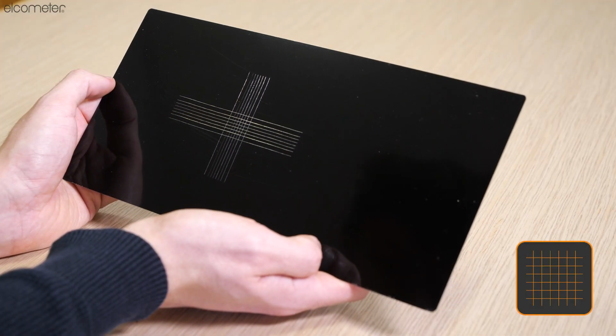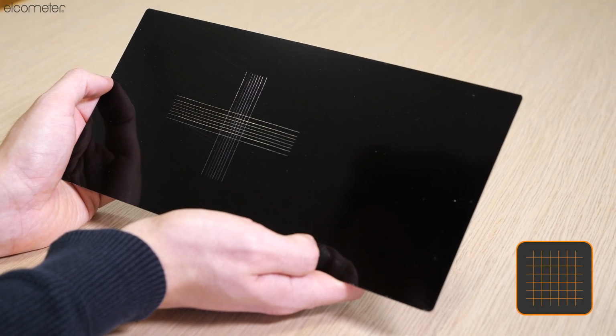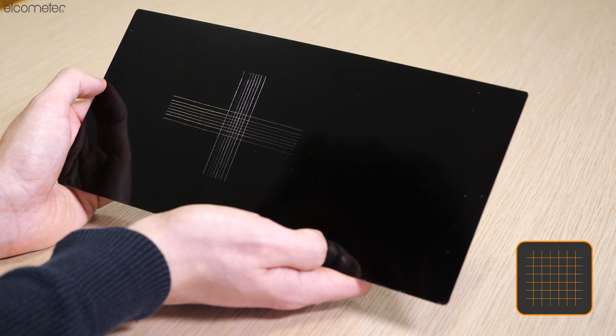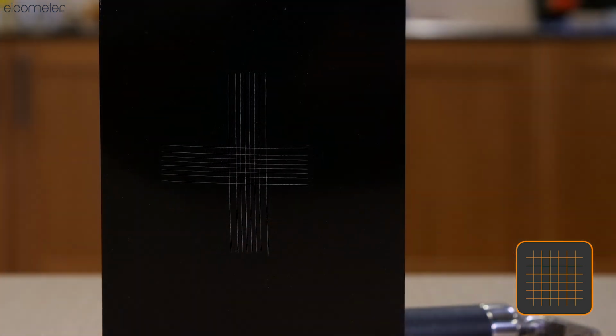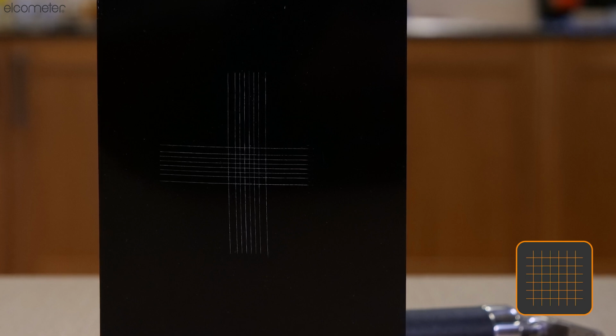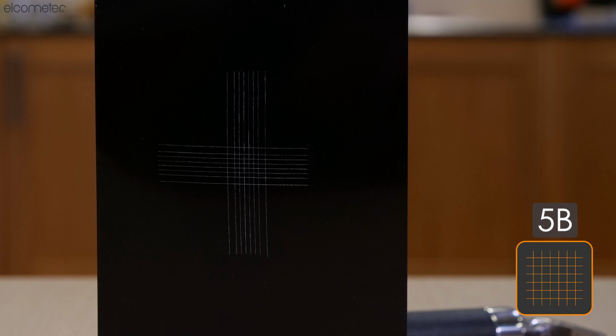As you can see from the results, the appearance of our substrate indicates strong coating adherence as the edges of the cuts are completely smooth and none of the lattice is detached. We can therefore record this as a 5B result in accordance with ASTM classifications and rest assured that the coating meets quality standards.